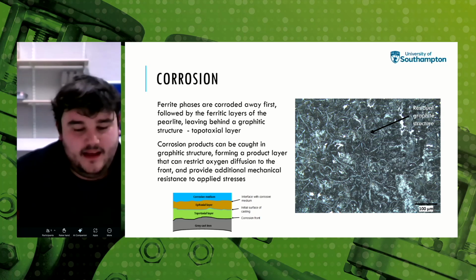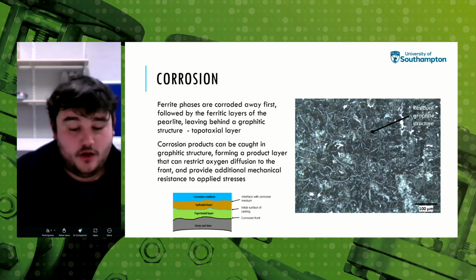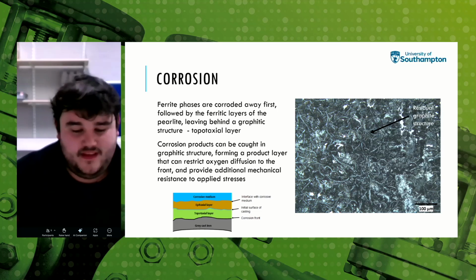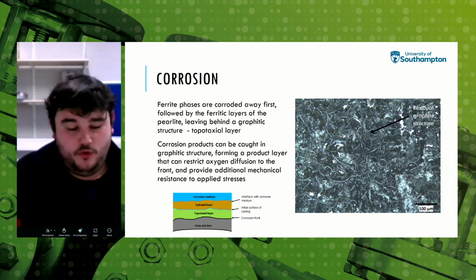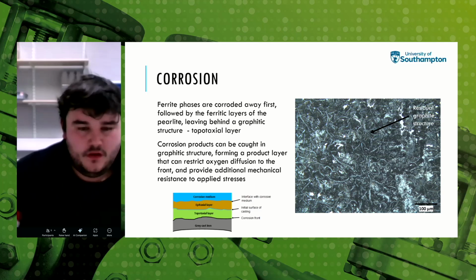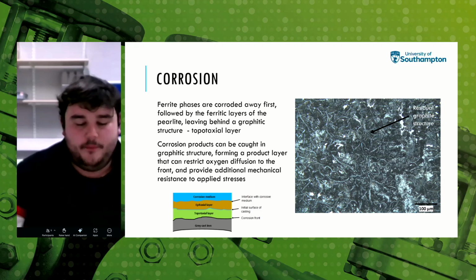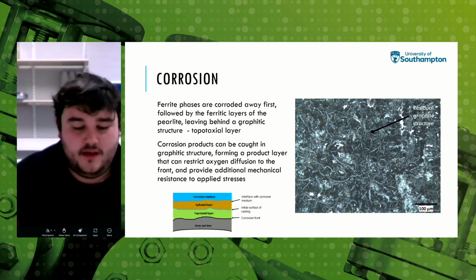Next slide, please. So as the reaction progresses through the material, you see that this ferrite is eaten away. But as the graphite flakes act as a cathode in the reaction, they remain untouched, leaving behind this residual graphitic structure you can see on the screen, what's also called a topotaxial layer. This layer can trap corrosion products that diffuse up from the corrosion front and compact over time into a coherent film, so a corrosion product film, that begins to restrict the diffusion of oxygen down to the corrosion front and therefore slow the reaction.